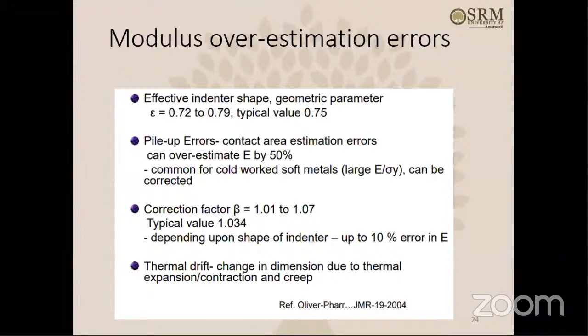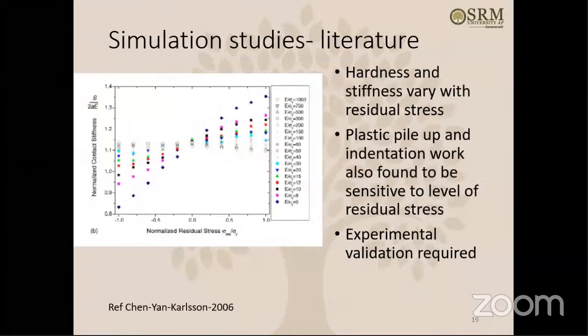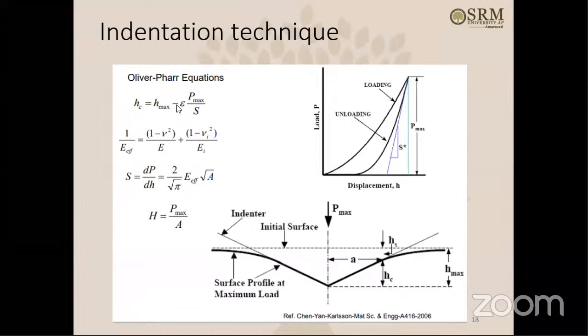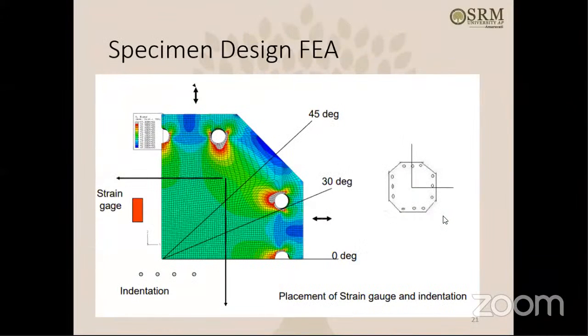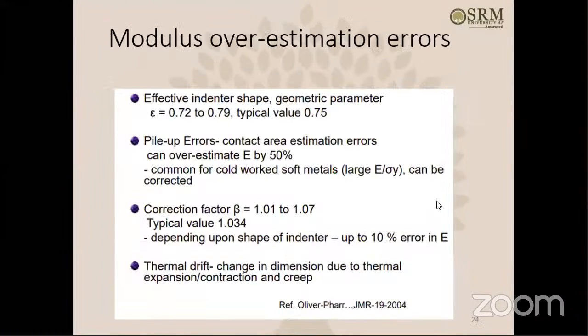Effective indenter shape, so there is one geometrical parameter, which ranges from 0.72 to 0.79. So depending upon that, what we should use. If you see here in the equation, the parameter will be there. Here, the parameter is there. Okay. So the parameter has a value and it affects the calculation.